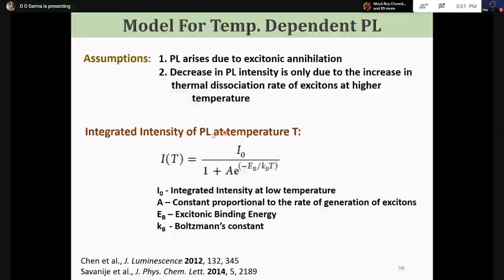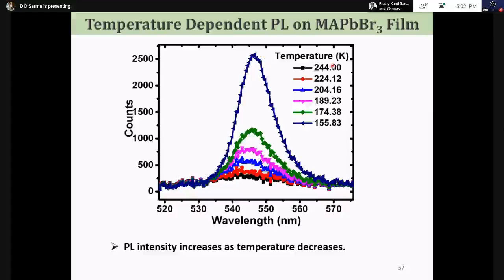And this can be formalized, and the expected dependency of the photoluminescence intensity as a function of temperature can be given by this, where you have an exponential dependency, and EB is the excitonic binding energy, essentially the barrier that you must overcome with the thermal energy kBT to break apart an exciton into a free electron and free hole. So all that you need to do is to measure the photoluminescence as a function of temperature, fit it to this equation, and get EB. Sounds very simple, and sure enough, if you do the experiment as a function of temperature, you can see that wonderfully there's a very strong dependence. At room temperature, it is here, and as you lower the temperature, it is going up so rapidly. So I should be able to extract the binding energy from here.